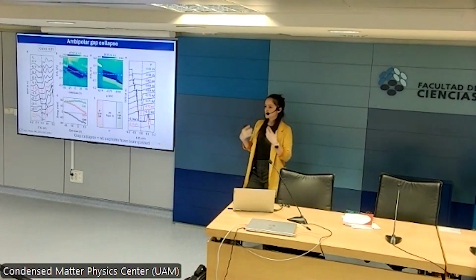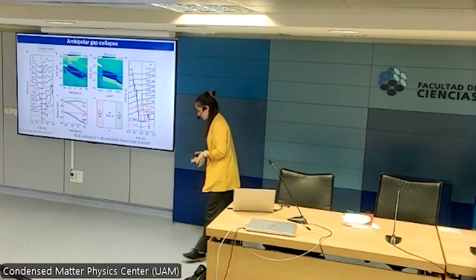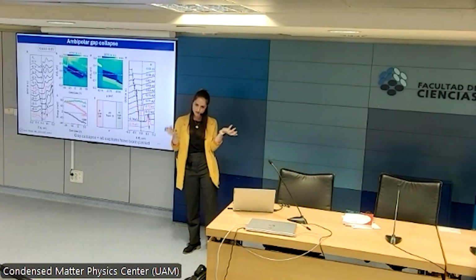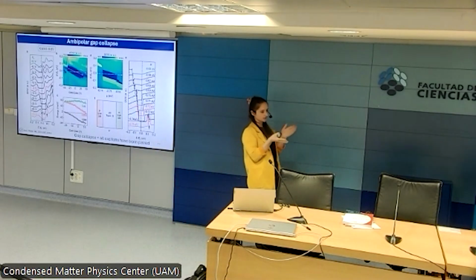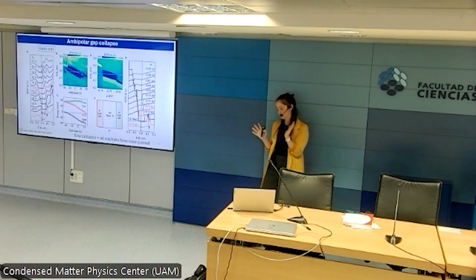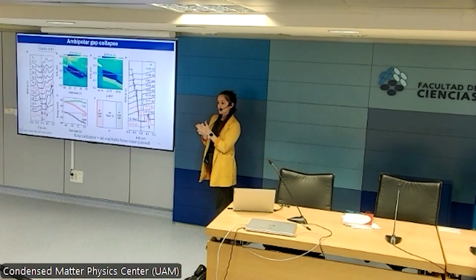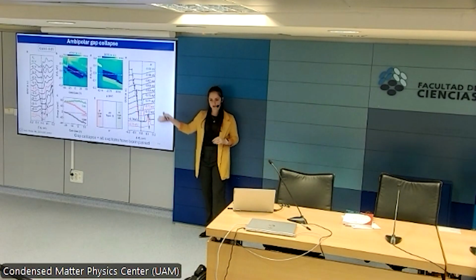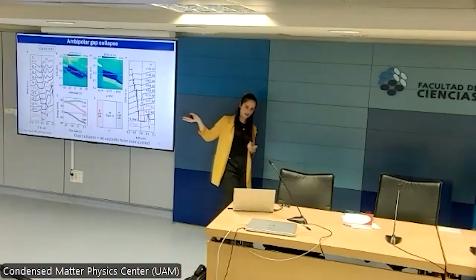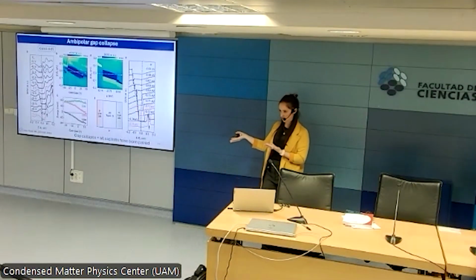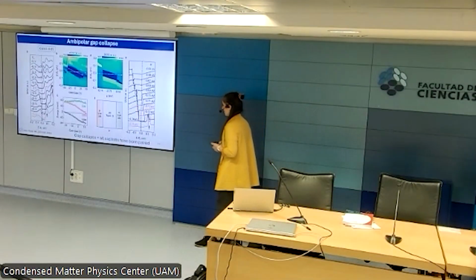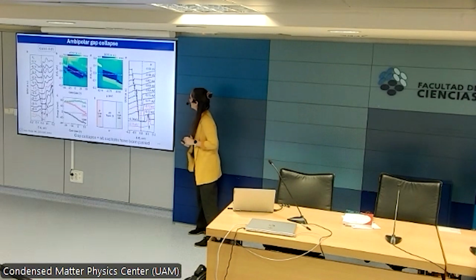And this is because as you gate, what you are doing is introducing carriers, positive or negative. At some point, all of your electrons will be paired up, all of your excitons will be paired up. No more excitons, no more band gap. So collapsing of the band gap demonstrates that your system is in an excitonic insulator state. This is all the premises.